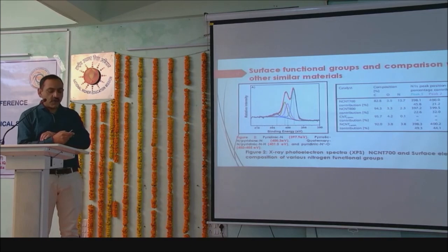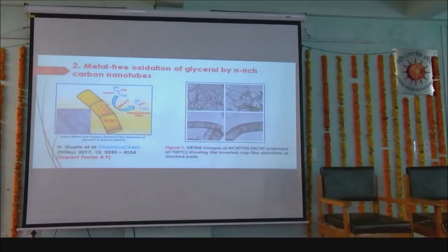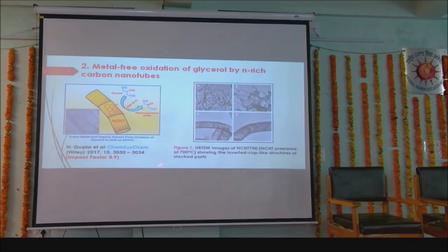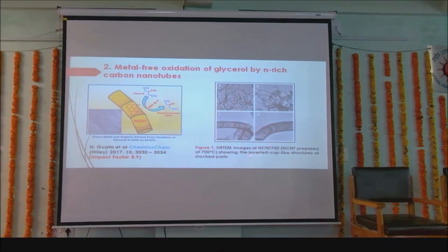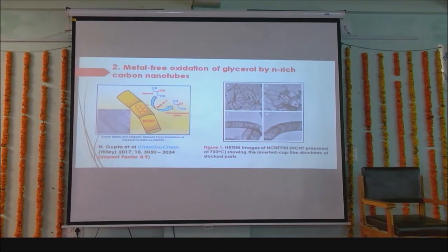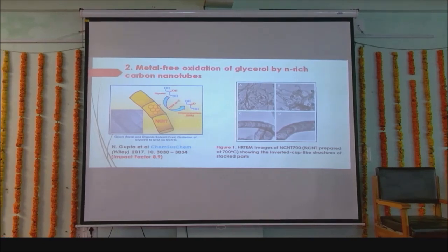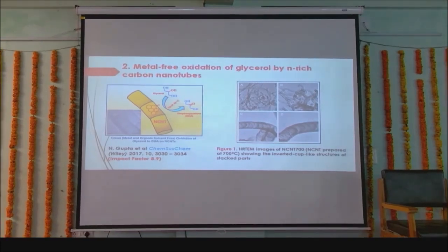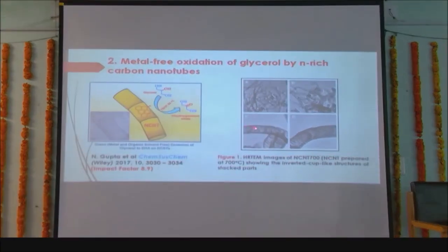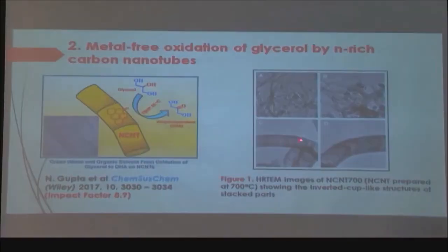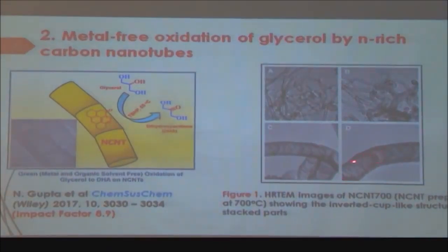So first of all, we make a catalyst where we have taken a nitrogen precursor, right, an organic molecule, and with the help of CVD we make these carbon nanotubes. How do these look? They look like cup-shaped material, you know, one cup stacked on another cup, another cup, something like that. If you see, it's a cup and one more inverted cup. So we see that it is a tube, because it is hollow from inside and open at the end. So we designate it as a carbon nanotube.